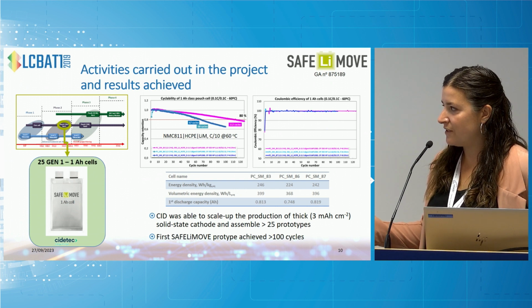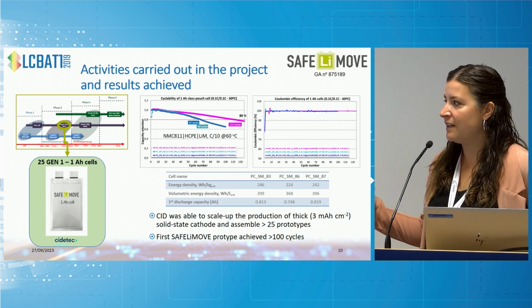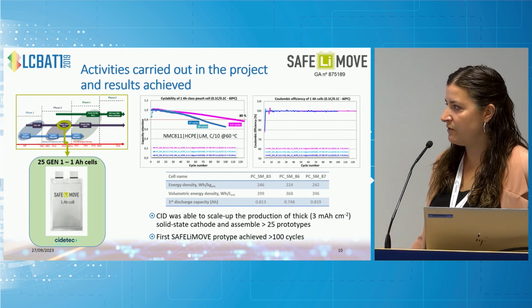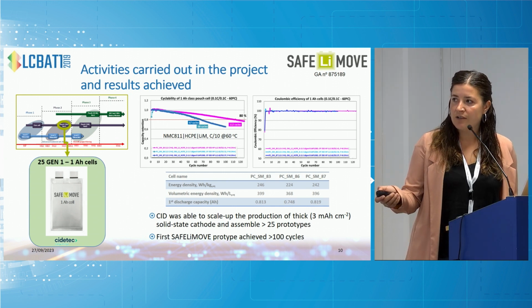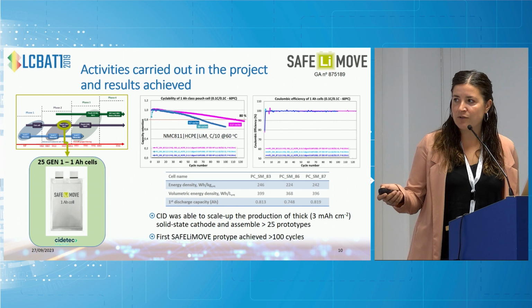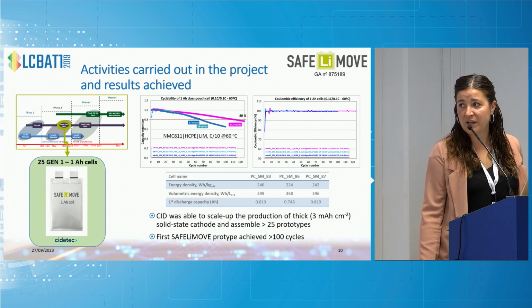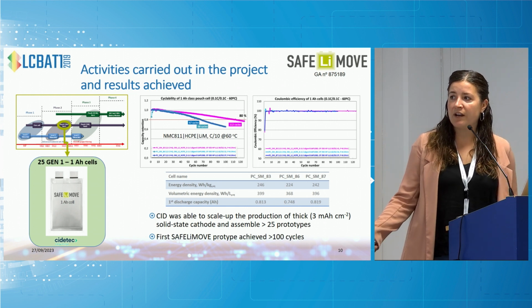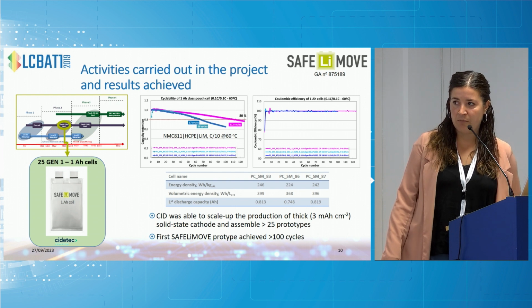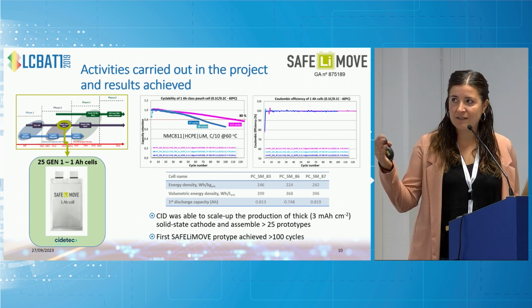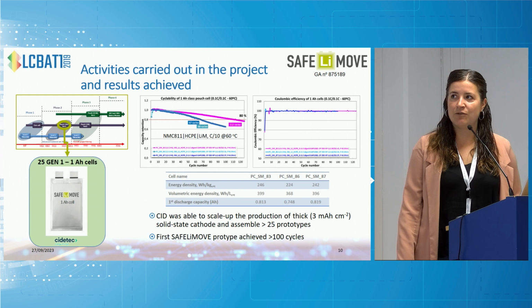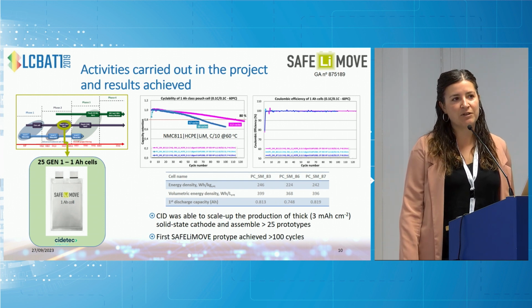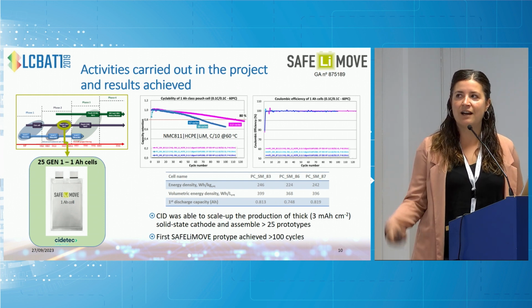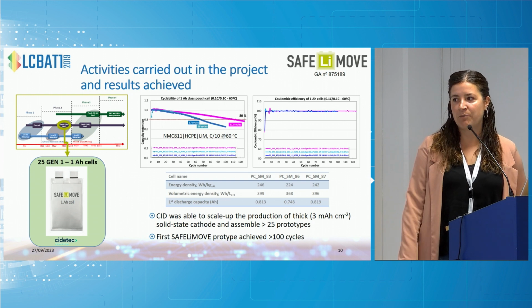So these are different replicates, proving that the energy density calculated from the first discharge cycle, we can see how we were in the range of 240 watt-hour per kg and 400 watt-hour per liter. So as I was saying before, this was one of the really important milestones within the project because we were scaling up all the components and having the first generation of our 1 ampere-hour cells.